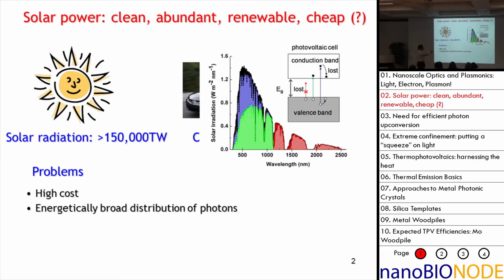But again, the vast majority of photons here are going to have excess energy over the band gap of silicon photocells, and they're going to lose this energy by thermalization because of the vast series of phonon states available in a typical bulk band gap semiconductor. So this is a big problem that ends up heating the semiconductor photocell. More than a third of energy here is just going to be dissipated as waste heat.